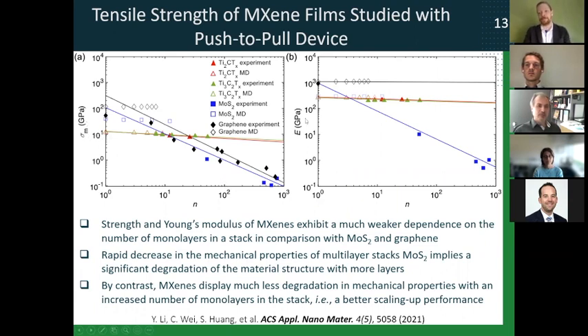Yeah, well, the difference is we plot different properties. So on the right-hand side, Young's modulus, here it's strength, right? On the left-hand side. And actually these data which are plotted for graphene and for MoS2 are combinations of experimental and modeling results for both materials. We have modeling as open symbols, and experiment as these blue or black ones, right? Now, as you see here for graphene, modeling shows that basically the scaling is similar to graphene, but this is modeling. Real experiments are these black diamonds, and they show that it goes down, right? This is in terms of the strengths.